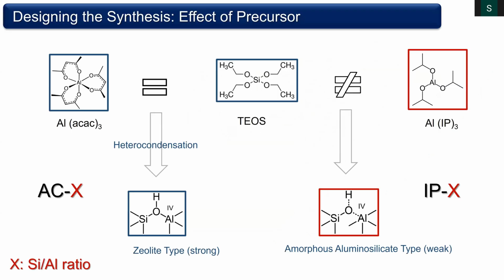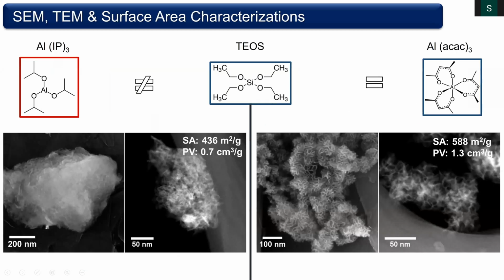So we use again the DFNS protocol to make this material, but we replace some of the TEOS starting material by the aluminum ACAC, and we make sure that they condense together to give you the zeolitic type bonds, which make it strongly acidic. And these are the normal characterizations like SEM. It looks like a sponge with a good surface area, 588, and very high pore volume for such a material, 1.3 cm³ per gram.